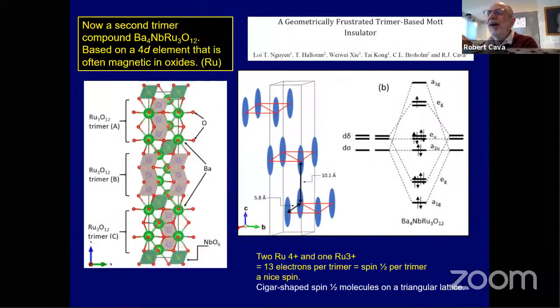I'm happy. Now, if I go to 4D elements in the trimer, it's not so clear anymore where the spins are. So now I have 2 ruthenium 4+ and 1 ruthenium 3+, but that's 13 electrons per trimer. And if you look at the orbitals in an isolated trimer, like a molecule, you get 1 unpaired electron. And so this thing is nominally a spin a half per trimer.